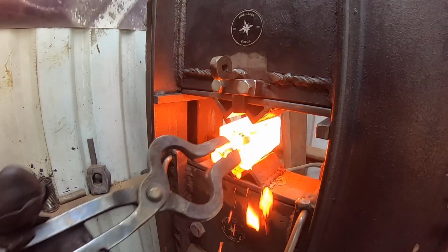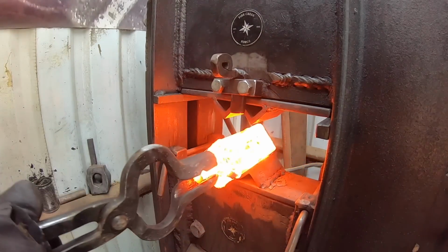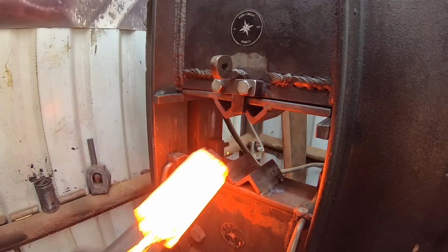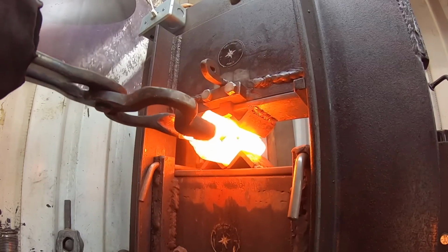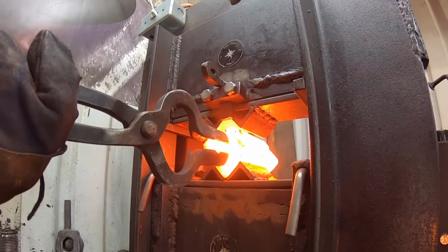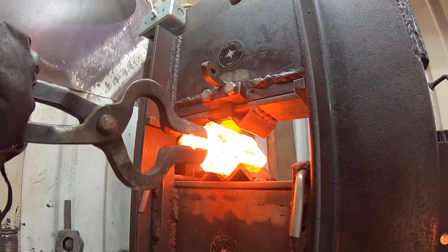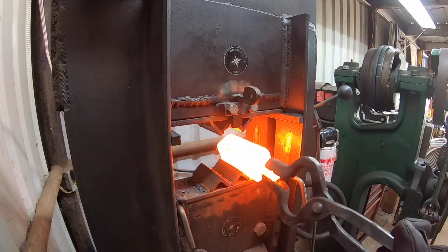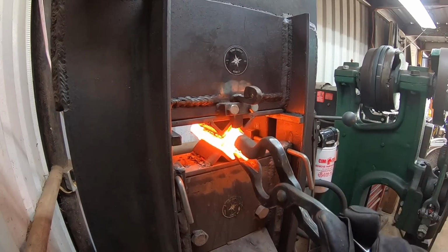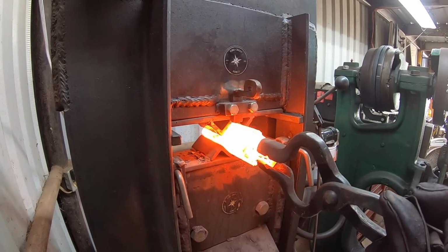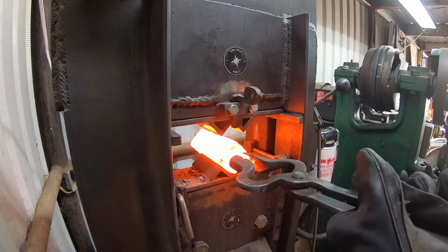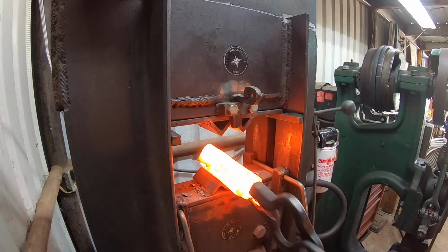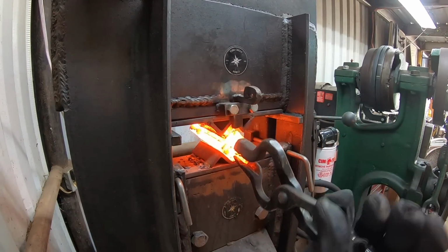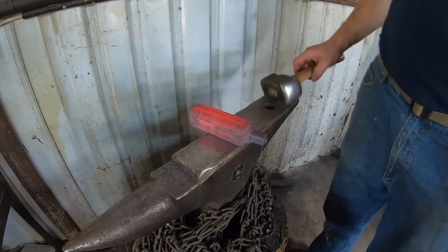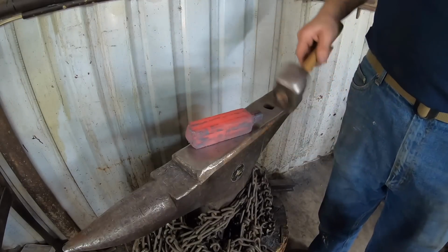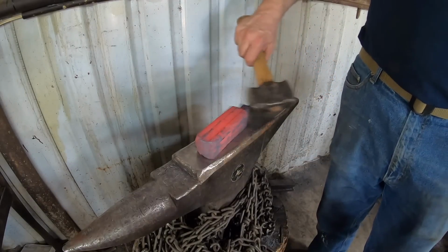Get it up to heat, and that takes about 20-30 minutes. Press it in the square dies, and you'll see the billet sticking in there, the can sticking in the dies. That's from residual flux that is stuck to the dies that came off the bottom of my other forge with other cans, and so there's no reason it should be sticking, and it's rather frustrating because there's no flux involved in this forge weld process and we're still dealing with it, but that's just the nature of the beast.